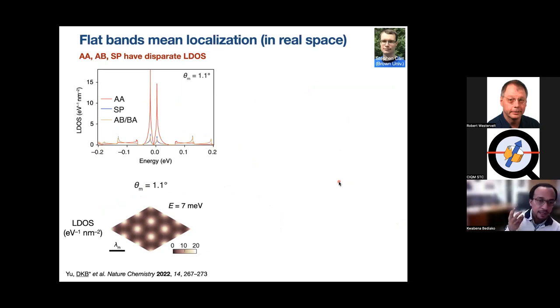What do these flat bands mean? Well, flat bands in our band structure, in real space, they mean localization, right? And so this is effectively what we see in the STM data. This is what other people have seen, other people have calculated. But just to show you, if you look at the local density of states for AA, saddle point, and AB or BA stacking, you see that at 1.1 degrees, your electronic states are strongly localized on the AA sites.